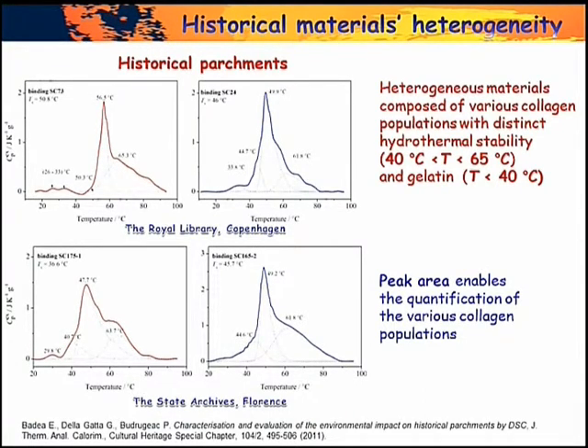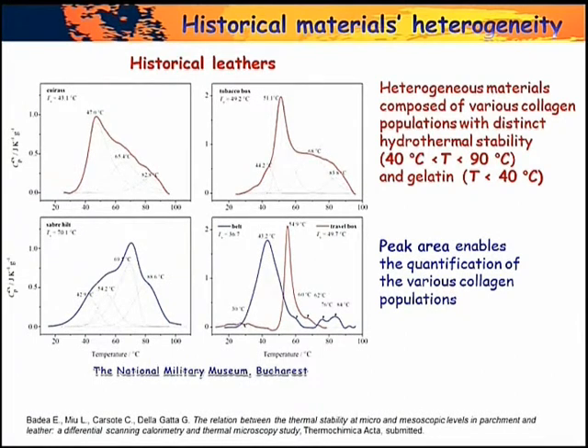These are the denaturation peaks for historical parchments. If we decompose a peak, we can see that there are distinct collagen populations which denaturate at a different temperature, okay? And this depends on the structure of this collagen population, and of course on the level of deterioration of the materials. Moreover, in this case, we can also quantify the various collagen populations by measuring the peak area of each of these peaks. Also, gelatin can be detected and quantified. The same in the case of leathers.